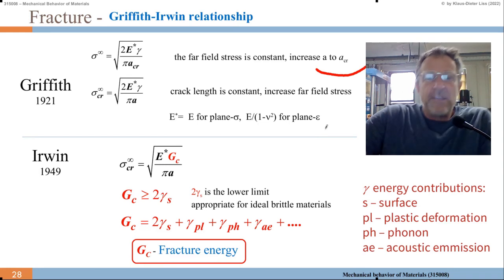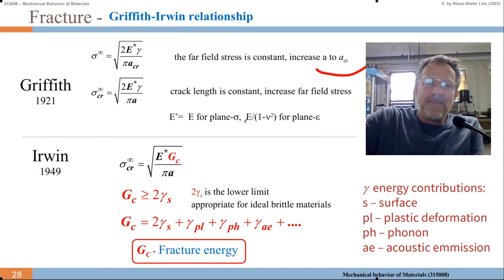So when we work it out, for plane strain E star is larger than for plane stress, because nu squared is smaller than 1, so 1 minus nu squared is smaller than 1. That's in the denominator, so it becomes a larger number than in the plane stress situation.